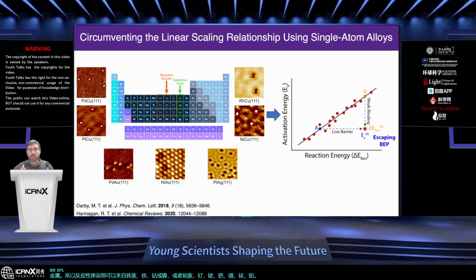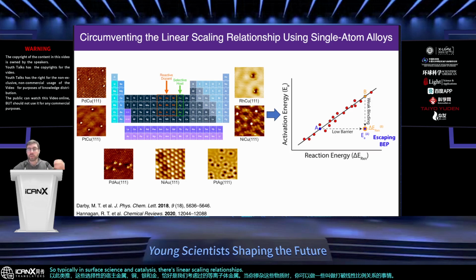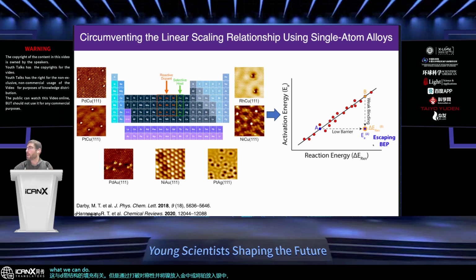So typically in surface science and catalysis, there's linear scaling relationships with the association of absorption of molecules onto a particular type of material. And this has to do with the filling of the D-band structure. But by breaking the symmetry and putting, let's say, nickel into gold or platinum into silver, what we can do is we can escape these Brønsted-Evans-Polanyi relationships, the BEP linear scaling relationships, and get activation energies that are no longer similar to the reaction energy that we expect from that linear law that's been dominating heterogeneous catalysis for the last 50 years or so. So we can lower individual barriers by creating active sites of platinum in a gold surface where that reaction typically wouldn't take place.